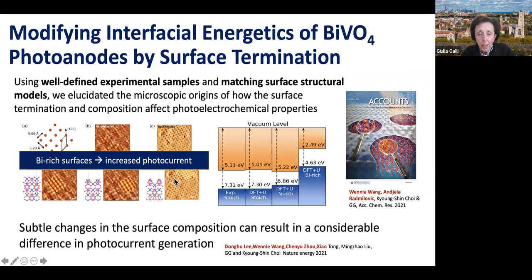But a question similar to yours is exactly the question that our experimentalist Kyoung-Shin Choi with W. Madison asked about: how do we control the photocurrent? How do we measure it? And depending on the surface termination. An explanation of these measurements that unfortunately I am not able to give you in real time here is actually in this paper, Accounts of Chemical Research, and also in the SIs, supplementary information of our paper in Nature Energy that came out at the beginning of this year. You will find an explanation on how they measure exactly the photocurrent and how it is controlled. It's not an easy business, but there are techniques to control exactly and to understand how to measure the photocurrent.